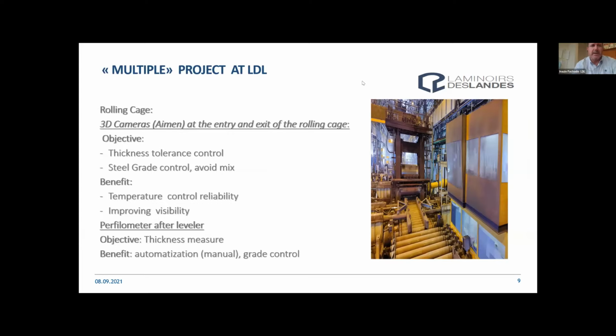And finally, in the rolling cage, we have installed 3D cameras at the entry and the exit of the rolling cage that will allow us to better control the thickness and also the steel grade. This way we will avoid that some slabs are loaded by mistake, and it is another checking point that will help. The benefit of these cameras will be that we will have more reliability when controlling the temperature.